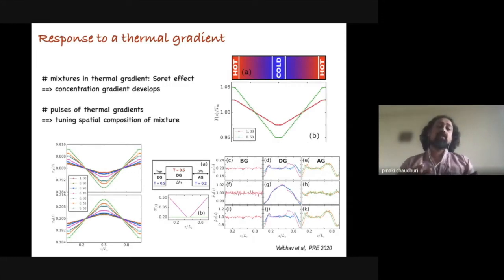What is interesting is that in mixtures, if I have a mixture of large particles and small particles, there is something called the Soret effect, a phenomenon where, if I have a thermal gradient in a mixture, a concentration gradient also develops. In other words, you will have preferential concentration of large particles in one zone and small particles in another zone. We illustrate this on the left-hand corner over here. If I look at the concentration of the A species and the B species, the A species are more concentrated at the hot zone, whereas the B species are more concentrated at the cold zone.